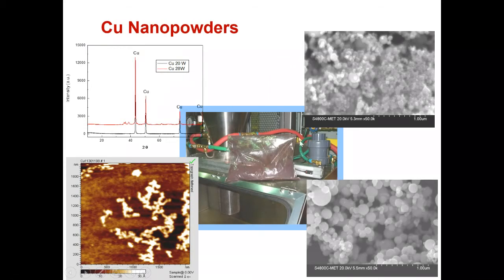A good indication of formation of copper nanoparticles is this: when the copper nanoparticles come out and get exposed to air, the temperature of that material goes up to 800, 900 degrees centigrade. It means oxidation is exothermic, and it will become red hot. So this is a good indication, and we observed it many times in the laboratory. One day, during our first and second run of copper nanoparticles, somebody opened the bag. As soon as that bag opened, it fell down on the carpet, and the carpet started burning. So it showed that the copper nanoparticles were formed.